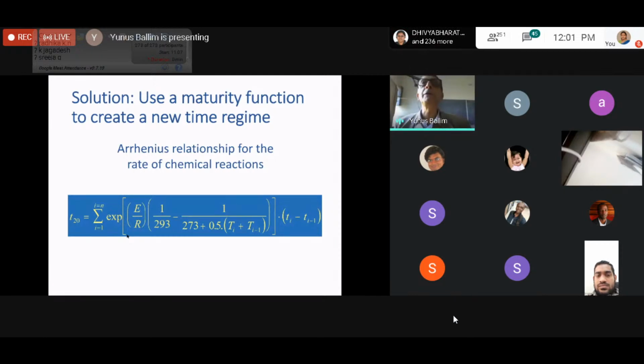Where what we did was we created a time scale where a second can be longer or shorter depending on the temperature. And that's called maturity. And we use the Arrhenius function, which is a fairly common function that is used in chemistry. And we normalize the Arrhenius function to 20 degrees C. Effectively, what we are saying is what would the hydration state have been had we kept the temperature at 20 degrees C. And that's really all this is doing.